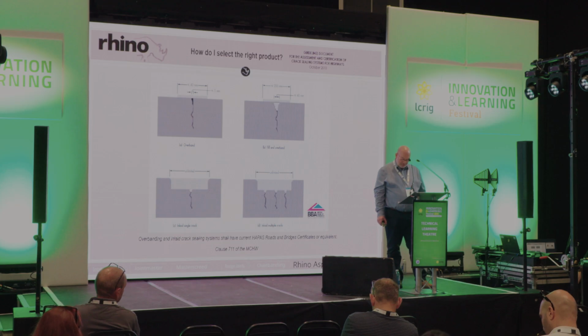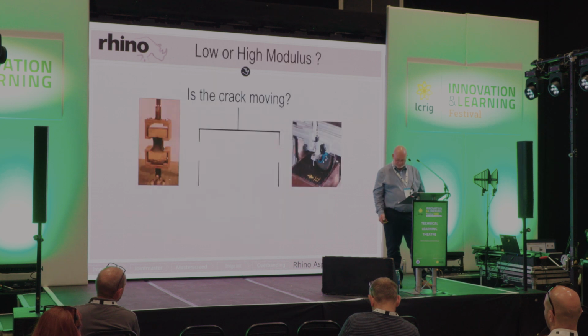In the bottom left, you'll see a single crack, an inlaid crack repair. Now, this is where the surface is milled out and the repair is inserted into the carriageway. And on the bottom right, you'll see a multiple repair where there's multiple cracking, and it's the same treatment with the inlaid treatment. This document also describes the type of materials to be used, whether they're high or low modulus. So what's that? High or low modulus?